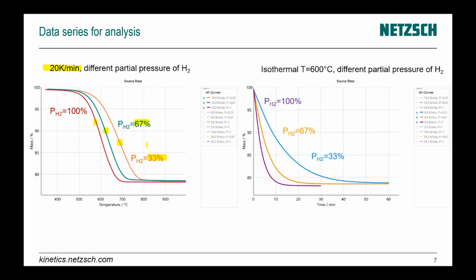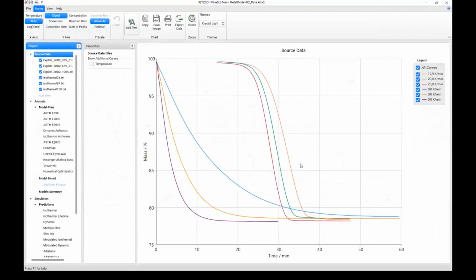This screenshot is from our Kinetics Neo software, and the same goes for all other screenshots in this presentation. The second set is isothermal data for 600 degrees C. Here again we have three different partial pressures of hydrogen: 33, 67, and 100%. Of course, in pure hydrogen the reaction is fast, and at lower concentrations of hydrogen the reaction is slow. And now let's go to our Kinetics Neo software.